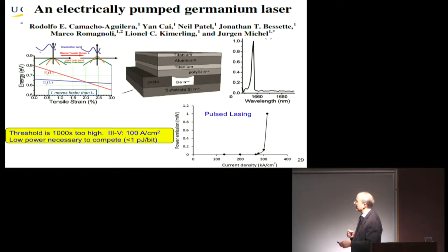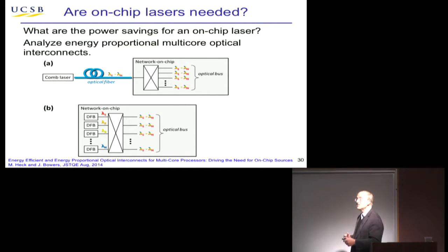So if you look here, this is work out of MIT. If you get enough strain in this material, you can make it direct bandgap. And if you make it direct bandgap, then it can be efficient. But it's not surprising that an indirect bandgap, everybody's still back here somewhere, is not very efficient and really isn't credible for use yet. So do you need an on-chip laser?